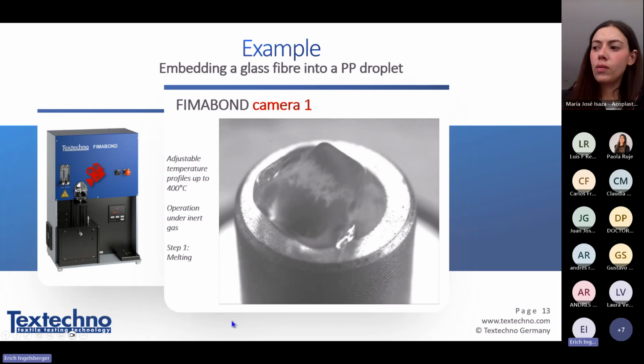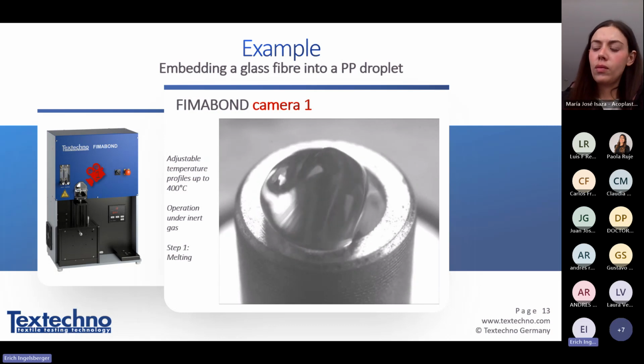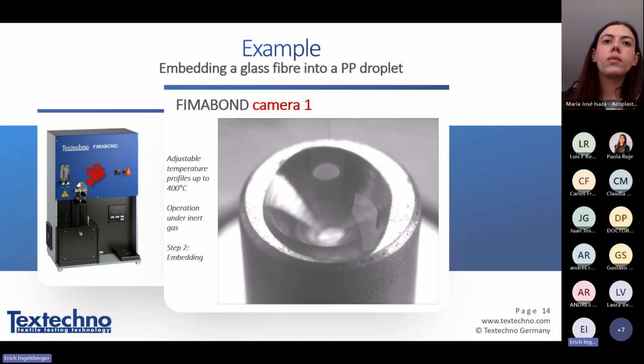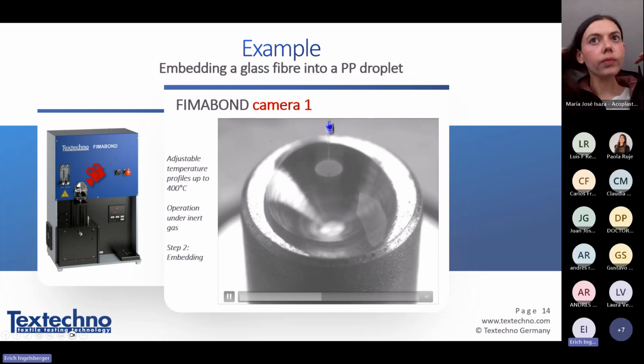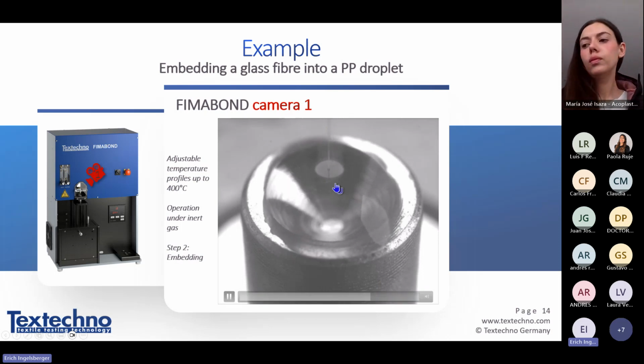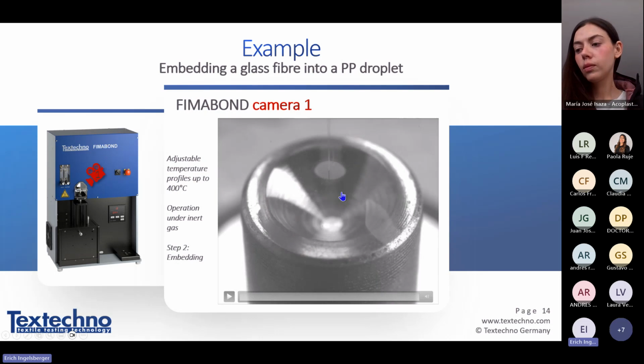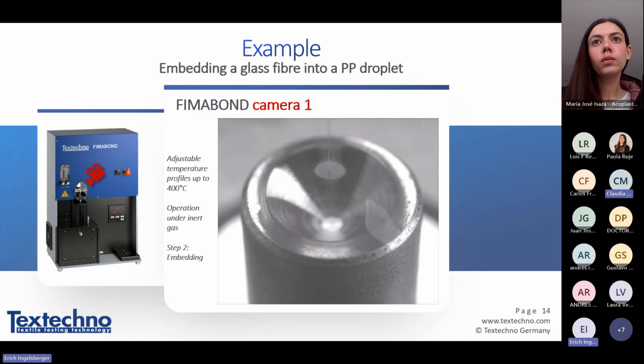So when, in this case of thermoplastic, the polypropylene is melted, the next step comes, and you see the fiber here. The fiber then touches exactly the center of this light reflection to be sure that the fiber is exactly on top of your matrix drop. So this is the embedding.